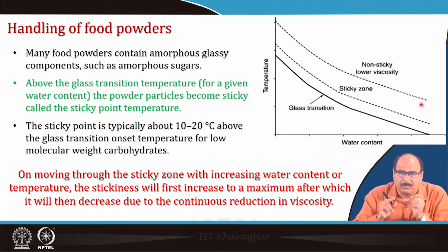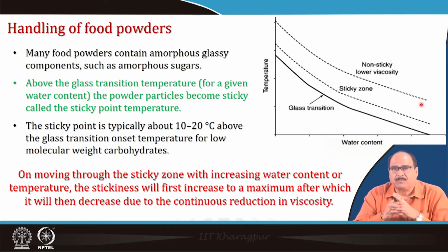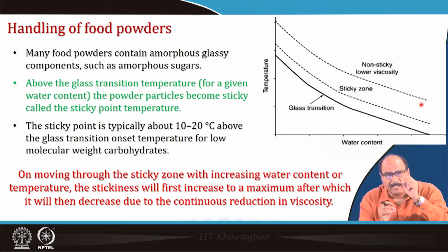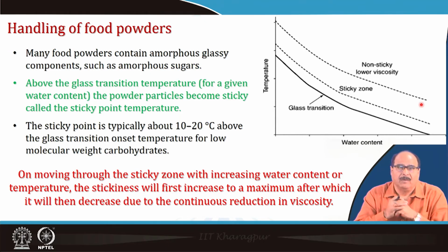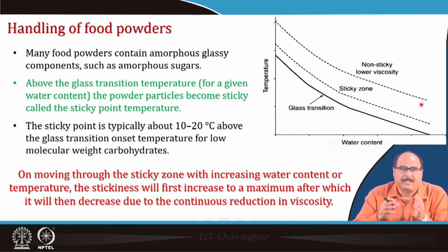As I discussed earlier when we were discussing spray drying or even drum drying for preparation of fruit juice powder, care has to be taken so that the material particle temperature does not go above its sticky point temperature or above its glass transition temperature. Sticky point is typically about 10 to 20 degrees Celsius above the glass transition onset temperature for low molecular weight carbohydrates, although it depends upon the composition of the material. On moving through the sticky zone with increasing water content or temperature, the stickiness will first increase to a maximum, after which it will decrease due to the continuous reduction in viscosity.